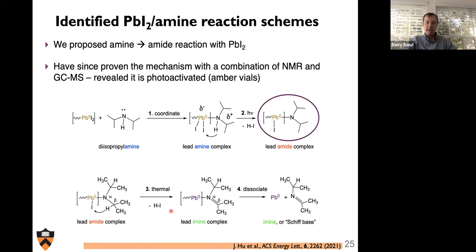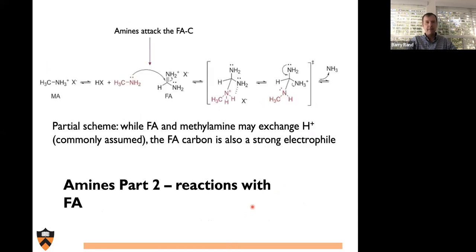This will happen spontaneously and lead to a lead imine complex, which is incredibly unstable, and so ultimately forms lead zero and this Schiff base or imine product. And these products were both isolated and found independently. And we found that indeed, if you have an amine coordinated to lead in the presence of light, it will lead to lead zero through this redox reaction. So that's the first step in the danger of exposing lead-2 systems to amines.